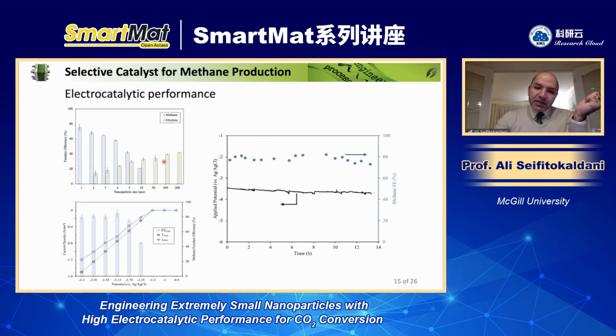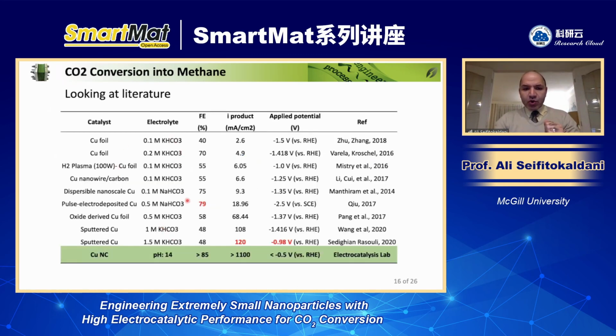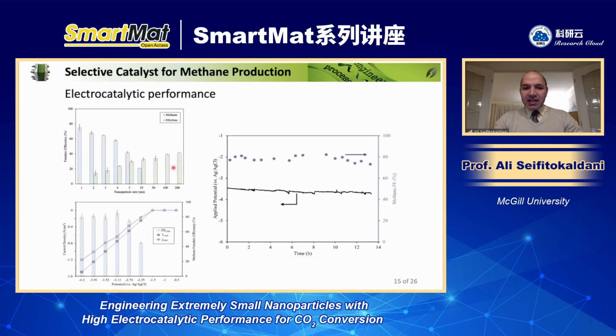And then when we decrease the particle size, you see that the ethylene selectivity decreases, and at very small particles, like 1 nanometer, you observe absolutely no ethylene. And then methane selectivity just ramps up and you observe more methane, which is very consistent with our DFT computations, showing that if you work in this range, you must have more methane than ethylene. And interestingly, this work is not even in neutral condition. So far, as I mentioned in this table, all these works are in neutral conditions or pH around 8 or 9 maximum. But here we are using 1 molar KOH with a pH of 13, 14.